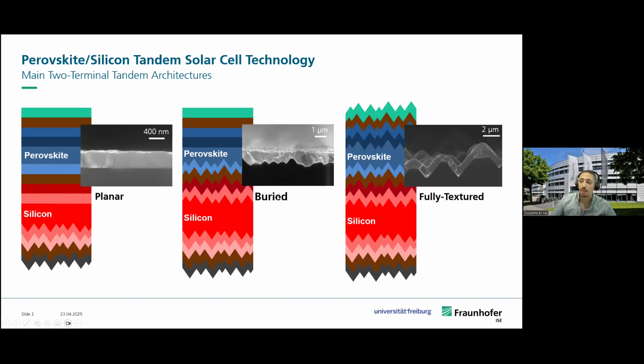We have the buried architecture, where again we use solution processing, but here it's done on top of textured silicon with a relatively small pyramid size, in a way that the thick perovskite absorber really submerges the textured silicon and the top surface is flat. And then we have the fully textured architecture, where the perovskite film actually conformally coats textured silicon with a pyramid size which is larger than 1 micrometer.